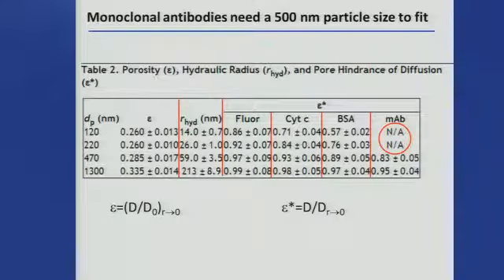And we did a fluorescence experiment, fluorescence recovery after photobleaching, where we looked at fluorescein, and then each of these was tagged with fluorescein so we could measure the diffusion coefficient. And we made the assumption, just based on the polymer literature, that the porosity would be the ratio of the diffusion coefficient that you measure in the material to the diffusion coefficient that you would measure outside the material. We measure each of those with FRAP the same way, same graduate student and everything. And so that's how we get the porosity.